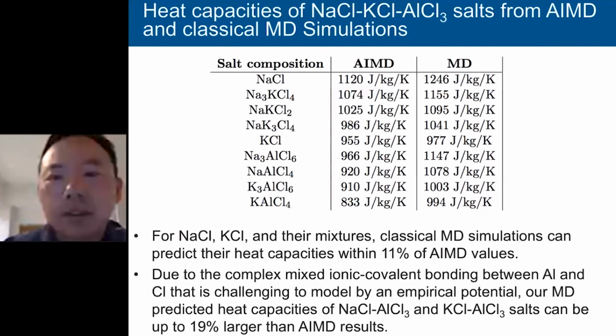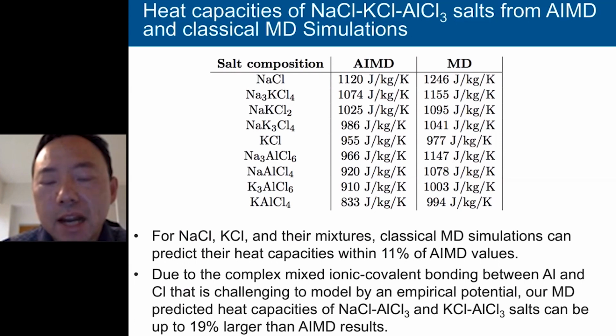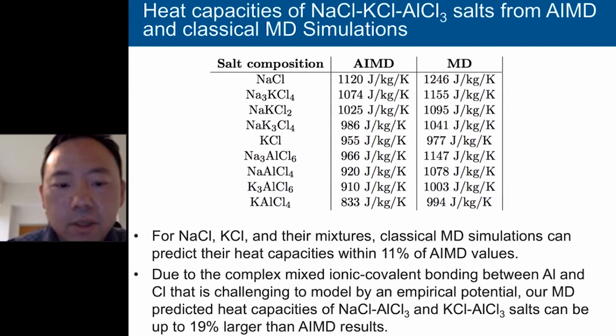Now let's go to the heat capacity. In this figure I show the Ab Initio calculated and the classical MD calculated heat capacity for the salts in these systems. For the sodium chloride and the potassium chloride systems and their mixtures, classical MD simulation can predict heat capacity within 11% error of Ab Initio MD results. Due to the complex bonding between aluminum and chloride, which challenges the empirical potential model, the error is somewhat larger for the systems involving aluminum chloride, and the error between Ab Initio MD and MD can be up to 19%, which is larger than the case of sodium chloride and the potassium chloride.